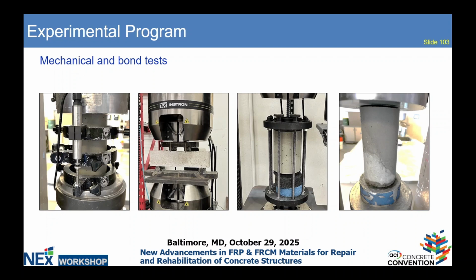So all of these specimens were tested on those 3 thermal conditions, and a baseline test was also performed. Actually, 2 baseline tests were performed, because one of them was performed at 7 days, and the other baseline test was performed on the day when all of those specimens were actually tested after thermal cycling.